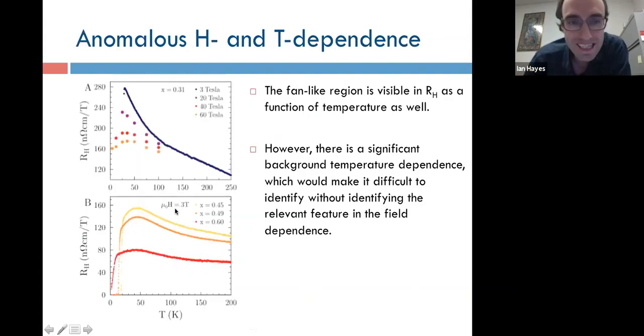And you can see this in the temperature dependence of the Hall effect as well, but it's a little trickier because of the background. This is one thing I really want to highlight about this use of the field dependence to characterize the strange metal behavior, is that it allows you to make sort of cleaner determinations about which part of the Hall coefficient is actually correlated with superconductivity and with proximity to the antiferromagnetic phase.